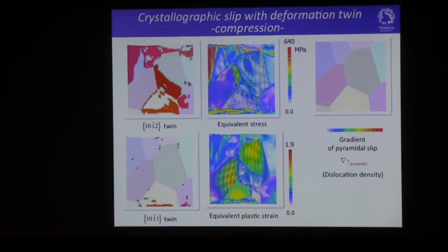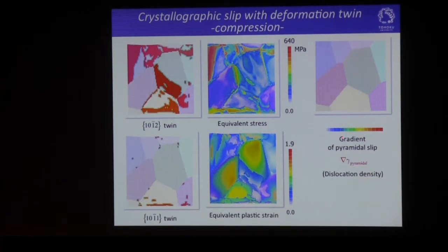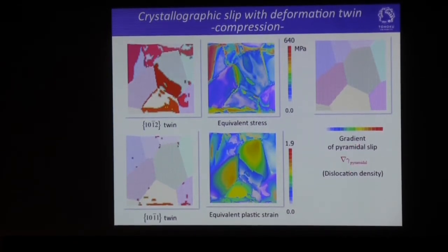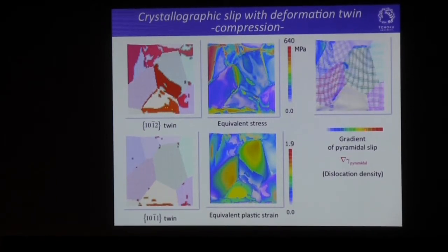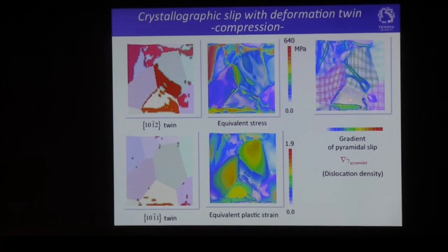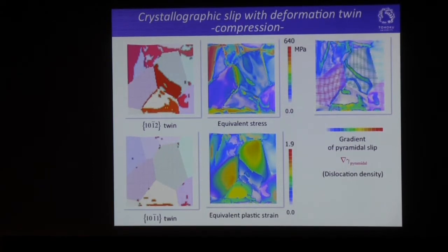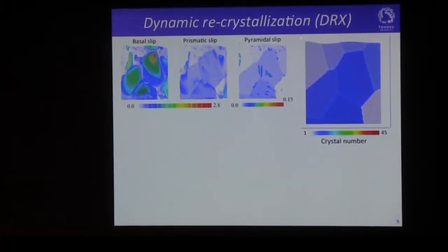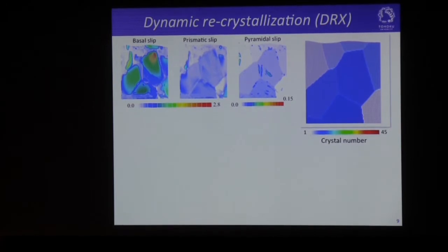At the same time, we could also have the distribution of the gradient of pyramidal slip we employed as a driving force of the dynamic recrystallization. This is just the dislocation density. This is the distribution of the gradient of pyramidal slip. Okay, so using this information, we could perform the dynamic recrystallization by using the multi-phase field method, like this.